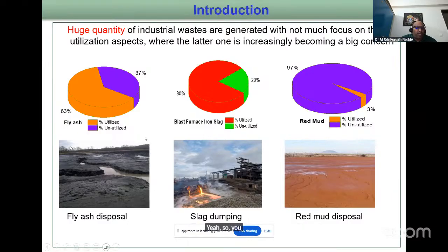Yeah. So you know the fly ash utilization ratios. Maybe it might have increased a little bit. This data is from maybe four or five years back. As per this data, fly ash utilization is around 63 to 64%, and the remaining 37% is left unutilized. And if we come to slag, 80% is utilized, because of Portland slag cement. Most of that waste material goes into the cement industry, and they use it as slag for manufacturing PSC cements. That's why utilization of slag is more, 80%. Then if you see red mud, utilization is very, very less. We can say only 3% worldwide. So yeah, these three contribute to the mix design of my research. Okay.